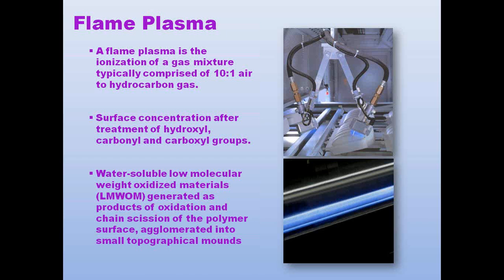When you treat a surface by flame, you are ultimately oxidizing the material. At the same time, there is a small amount of low molecular weight organic material, or globules of these different types of depositions, that will occur along with the oxidation on the surface of the material. It is a high velocity discharge, so the impact of the species on the surface will create chain scission at the surface of the polymer and create these small globules or topographical mounds at the surface of the material. And yet, as a result of that discharge, we get not only a grafting of carbon-based groups, but we're also getting longevity of treatment, and you get the functionality that you're desiring with that treatment.